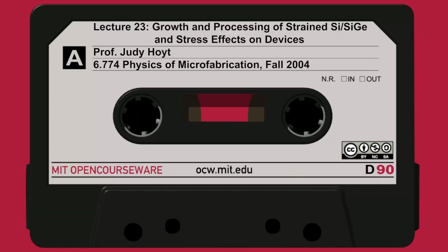Now, if that layer were unstrained bulk silicon, if you just take a wafer of bulk silicon and subject it to Raman scattering, you get a line at 521 inverse centimeters. It turns out the shift between the strained silicon peak and 521 is a measure of the amount of strain. So this is a very nice way. You can oxidize a wafer, strip the oxide, and check the strained silicon to see if the strain is still there. In fact, you can figure out the relaxed silicon germanium content as well using this.